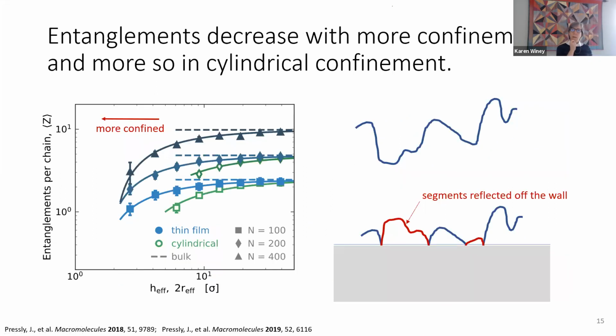We also looked at the entanglements because, like I said, polymer diffusion is associated with the entanglement density of the network. So you can see here the entanglements per chain as a function of these two parameters. The thin films and cylinders are on the same plot. Green is always cylinders, and these are different molecular weights. The dashed line tells us what it is in the bulk. And as we go to a thinner film or a smaller radius, these tilt downward. If we look at this molecular weight of 100 beads, this reduction in the number of entanglements is more significant in the cylinders than in the thin film.